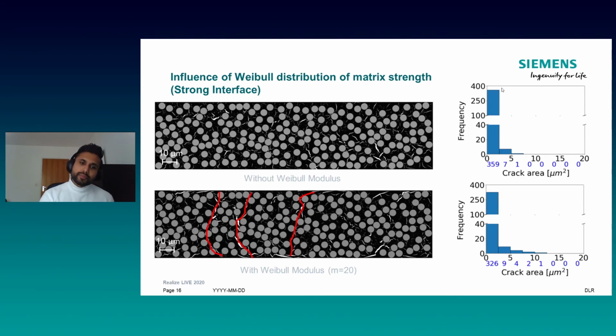For example, what we are seeing here is that the small cracks are coming together to form a larger crack. And this is evident from the statistics as well. If we see here, the number of small cracks has reduced from 360 to 326. And as you see, there are a couple of cracks which have a larger area when compared to the model without Weibull modulus. So this means there's a trend towards the formation of these carbon-carbon blocks which we desire for our microstructure.